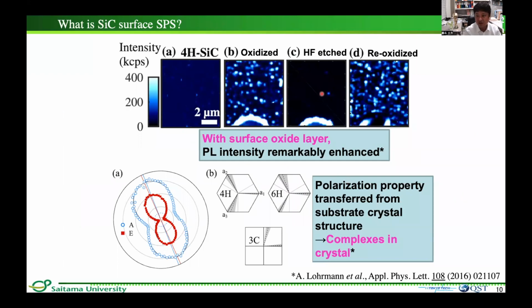These figures show PL maps before and after oxidation, and oxide removal, and oxidation again. Before oxidation, we don't see any SPS. But after oxidation, a lot of SPS appeared, like this. When removing the oxide layer, single photon intensity remarkably reduced. And SPS appeared again after reoxidation.